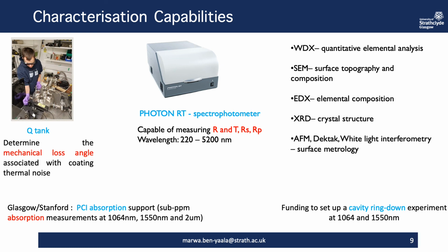We also have a Q-tank setup developed by our group for measuring the mechanical loss associated with the coating thermal noise. And we have access at the University of Strathclyde to several other characterization methods, including WDX for quantitative elemental analysis of the thin film, EDX for the elemental composition also, XRD for the crystal structure, and AFM, Dektak, and white light interferometry for surface topography.